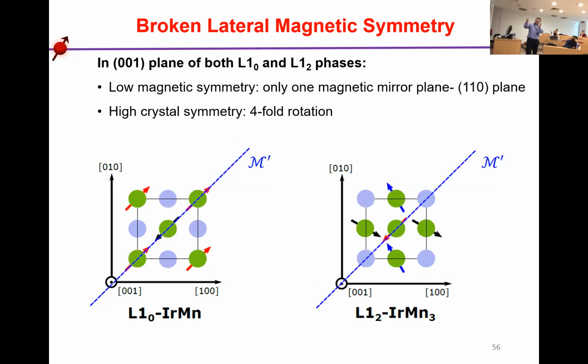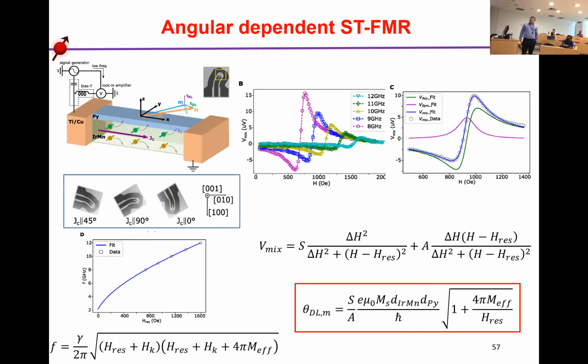So actually, when we do some detailed analysis for this L12 and L10 phase IrMn, we find out there exists a mirror plane, which is a 110 plane. So from here, the magnetic symmetry is lower than the crystal symmetry. The high crystal symmetry has a 4-fold, but for the magnetic symmetry, there is a mirror plane on the 110. So we use the angular dependent STFMR to demonstrate the existence of the out-of-plane spin polarization.